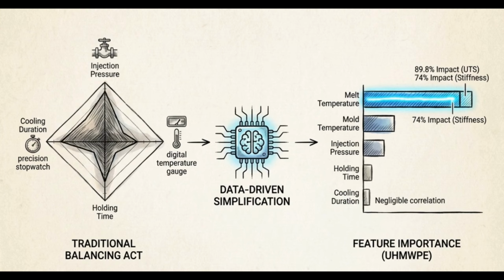The data simplifies this equation. When we run these variables through an ensemble machine learning model, melt temperature emerges as the overwhelmingly dominant factor. It drives nearly 90% of the ultimate tensile strength and 74% of the material's stiffness. Conversely, adjustments to holding times and cooling durations barely register. Their predictive correlation approaches zero.